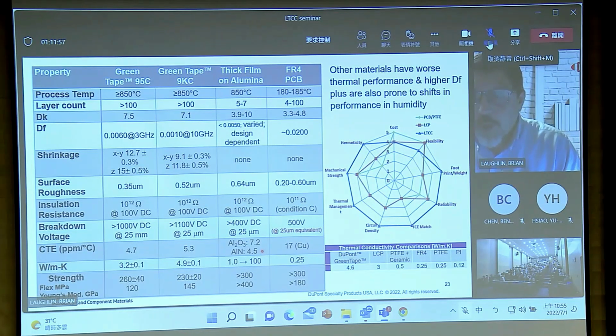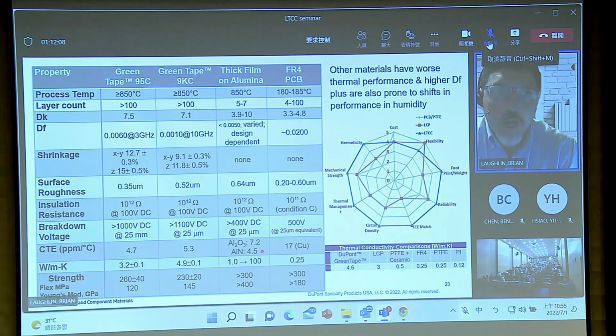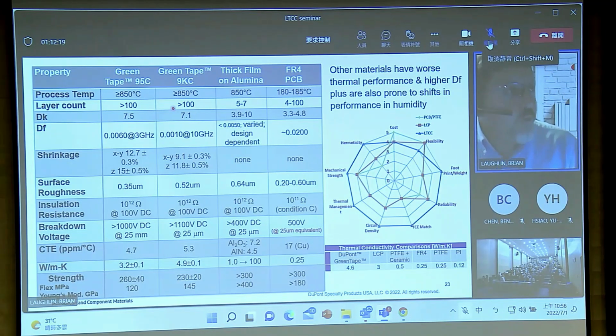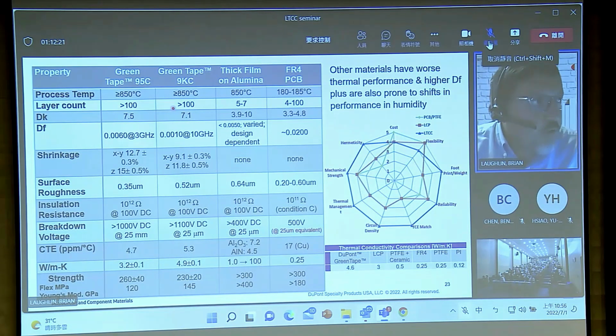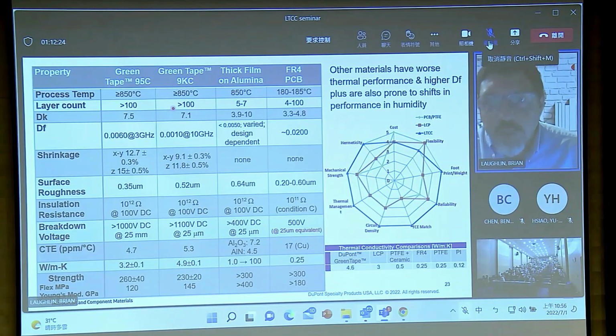And so I want to contrast it to what else you could choose besides our 95C or 9KC LTCC material. There's a lot of data on this chart. So I put here Green Tape 95C, 9KC. Some of it is repeated here. I put the process temperature. You can go above 100 layers if you want to in LTCC. Most practical modules are between 4 and 12 layers. Dielectric constant, loss, shrinkage, everything you've seen before.